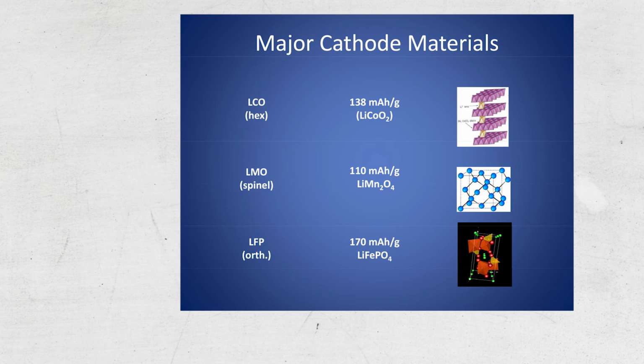There is another family of materials called the spinel cathode materials. The number one example of this family is lithium manganese spinel, LiMn2O4. It has this spinel cubic structure. And you have the lithium iron phosphate. And when you hear phosphate in Morocco, that means something, okay? Because we have the OCP, which is the number one exporting company in the world for phosphate. Lithium iron phosphate and others of the same family have the orthorhombic structure or symmetry, and it can intercalate lithium into channels. So these materials correspond to almost 99% of the materials that are used in commercial lithium-ion batteries.